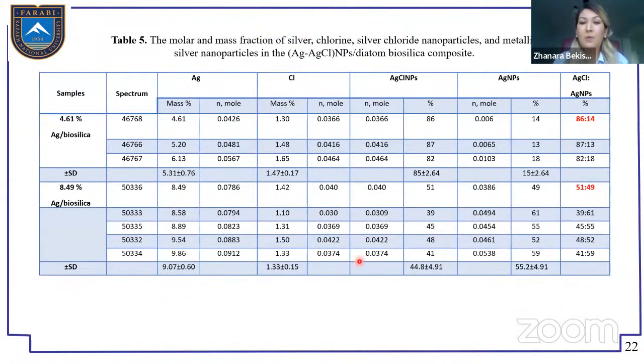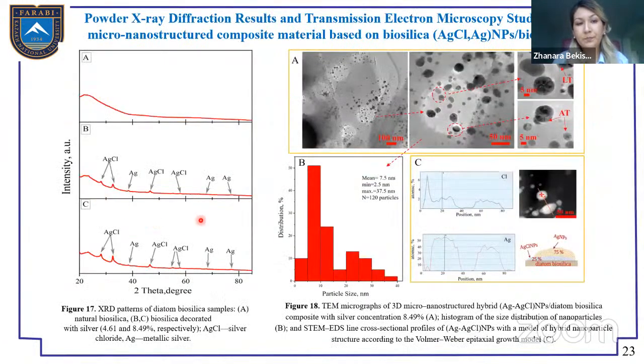And this is of hybrid particles and hybrid composite with content of metallic silver and silver chloride nanoparticles. And this is the ratio between the two particles, silver chloride to silver nanoparticles, equal to 86 to 14 and 51 to 49 for the two composites.